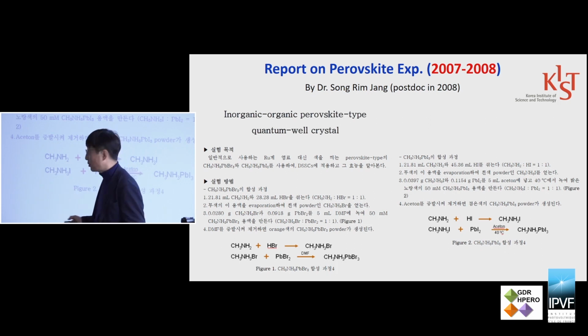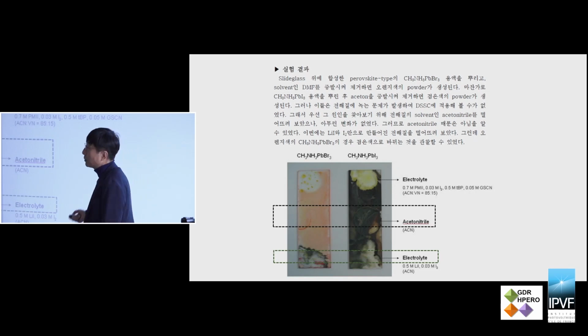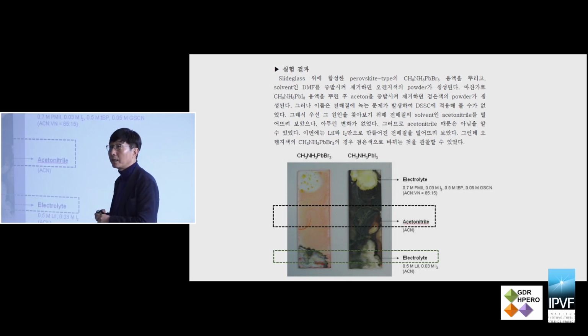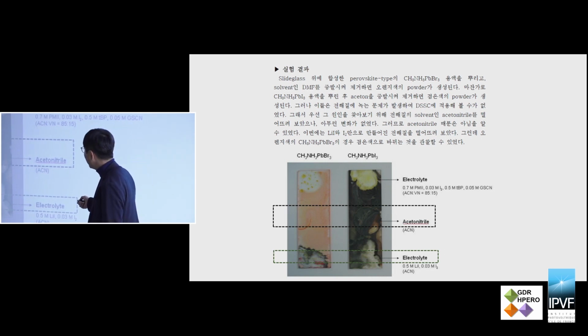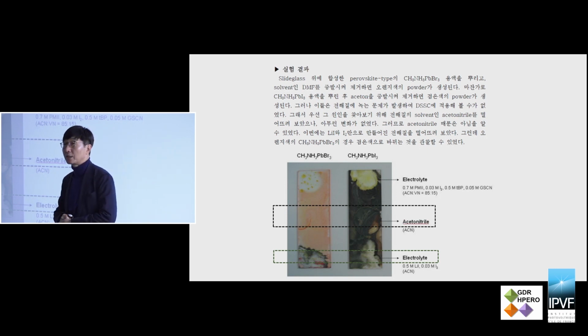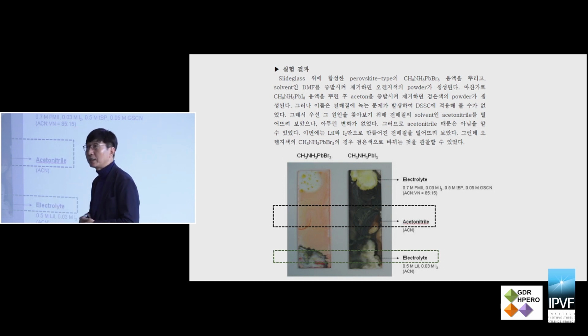So this is not so important, the result is important. Because she was an expert in dye-sensitized solar cells, especially the liquid type, she wanted to see what was going on in terms of the stability of this material. This material is an ionic crystal, so maybe it is not stable in the polar liquid electrolyte. So she prepared a thin film on plain glass and then dropped the electrolyte, and immediately the perovskite disappeared because of quick dissolution in the presence of the polar liquid electrolyte.